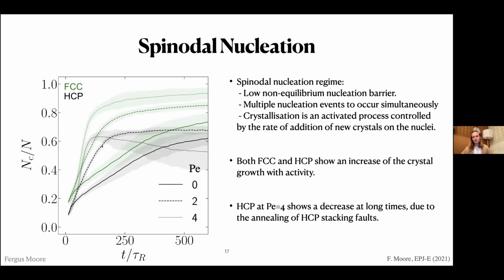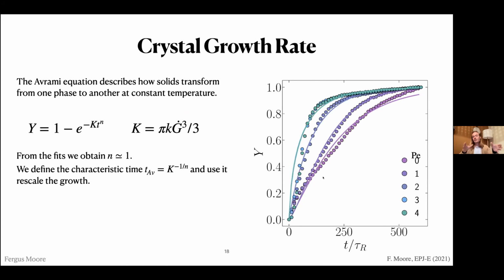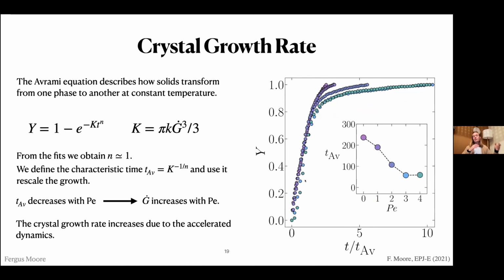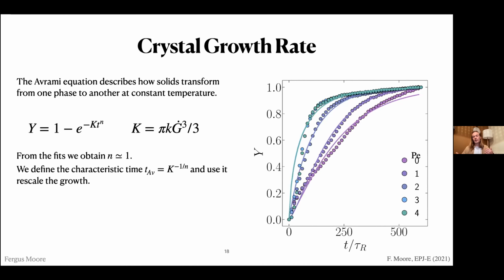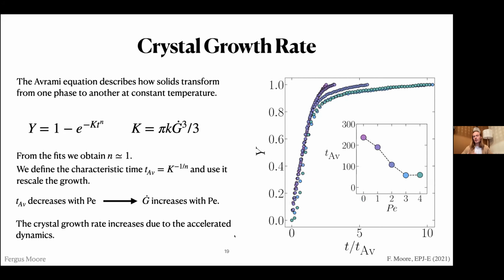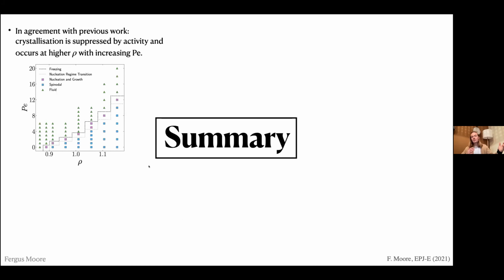So we can further analyze this by, my slides have crashed, unfortunately. Oh, there we go. We can fit these with the Avrami equation, which describes how solids transform from one phase to another. In this equation, we have this Avrami constant K, which includes the crystal nucleation rate and the growth rate G dot. From these fits, we can define this characteristic time, which is useful because if we collapse the curves onto each other, this time scale that causes this collapse decreases, since it's proportional to the growth rate, which tells us that the growth rate does indeed increase due to the accelerated dynamics in the melt.